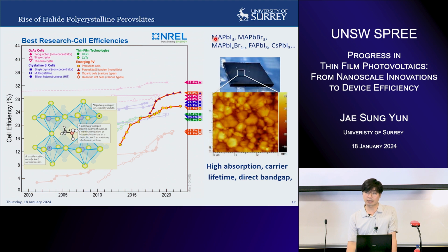So you can see that we can combine many different compositions. We can have methylammonium as the organic cation, lead and iodine, or we can even have bromide, and we can mix them as you like. But they will give you a different morphology, different crystal structure, and different band gap.